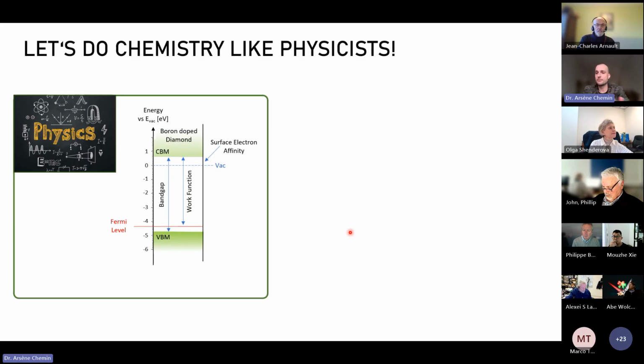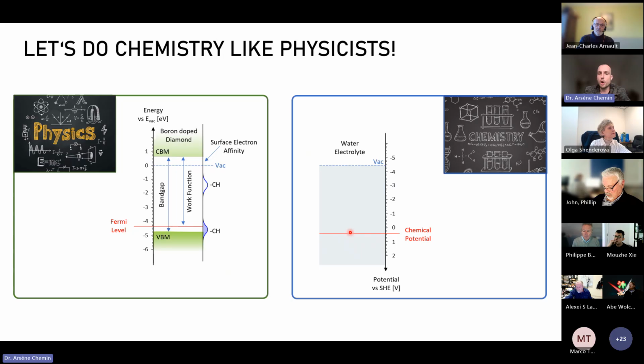And we can do exactly the same reasoning with diamond and the environment. So on one side, you will have the physics of the diamond with the valence band and the conduction band positioned according to the vacuum level, depending on the surface electron affinity, as I was talking about. And on the other side, you will have the electrolyte, so the chemistry part. And in the electrolyte, what will play the role of the Fermi level is actually the chemical potential. So in the case of water, this chemical potential is around 0 or 1 versus hydrogen.